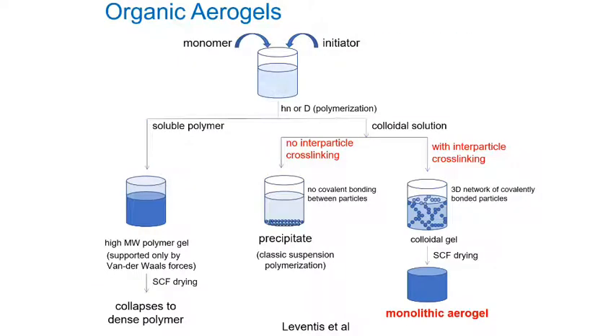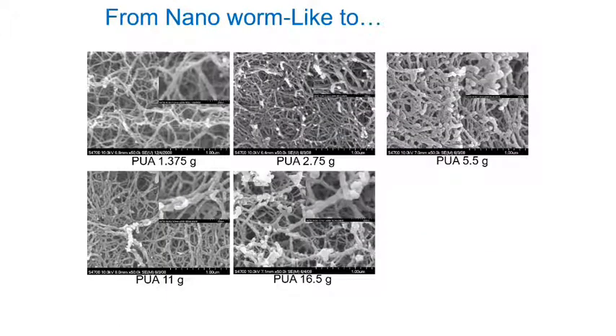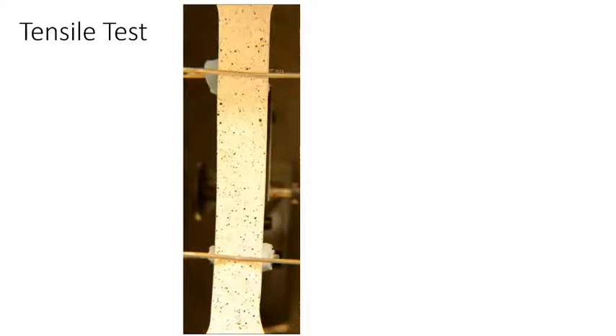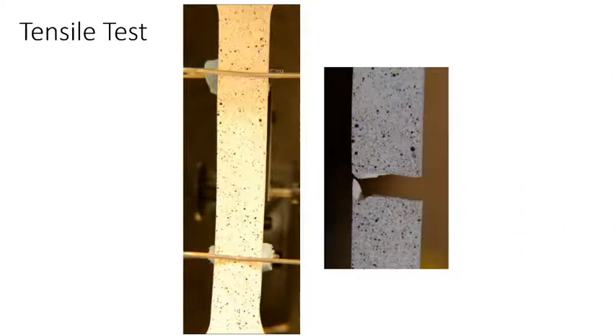So right now I'm going to talk about the organic aerogel, and similar to what we saw with the silica aerogel, you mix two things, and you can either form a gel or a precipitate, and then when you do supercritical drying, you end up with this. And these are some of the morphologies that we have done in the past. We also, of course, do a lot of these tensile tests, which I hope we can do here. And in this case, these are some of the biggest samples that we have been able to do.